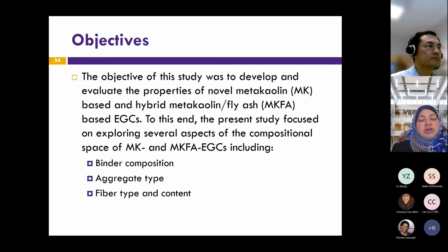So what was our objective here? We wanted to develop EGCs that are based on either metakaolin or a hybrid metakaolin fly ash base. And to achieve this, we changed the binder composition, aggregate type, and fiber type and content that was used.